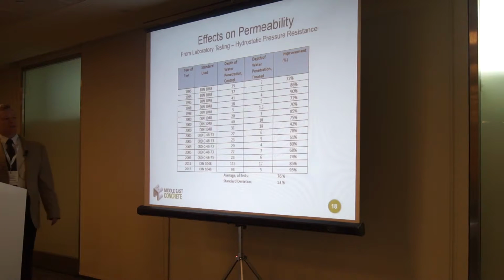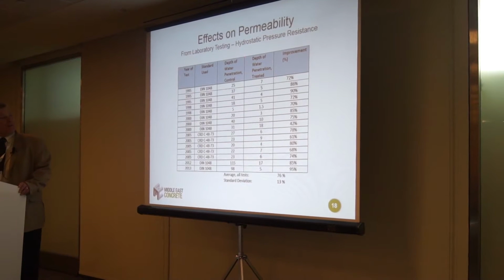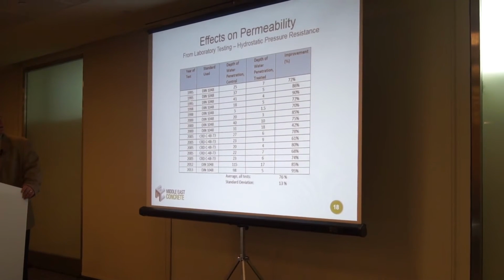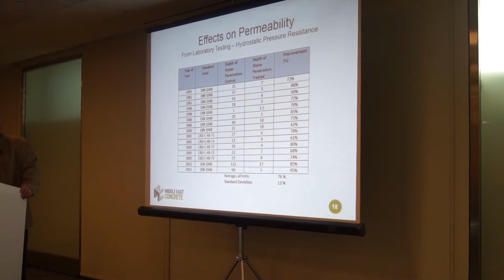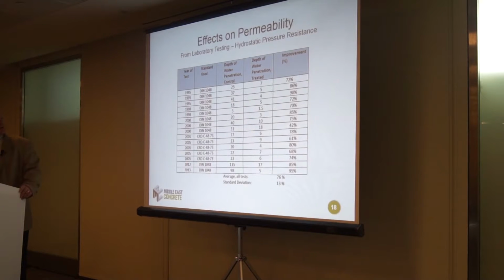So this testing was done under hydrostatic pressure. The DIN 1048 test, you can set it at different pressures, but I think we ran it at 7 bar, just to give you an idea of how the concrete will behave under hydrostatic pressure. And you can see the improvements have been significant. And of course I did not do these tests here. This was done in previous laboratories. But you can see on up to here, DIN 1048.